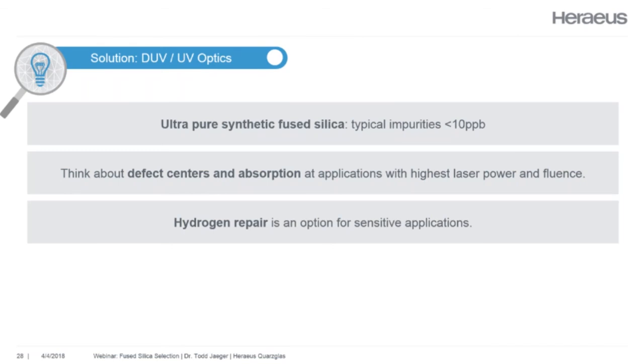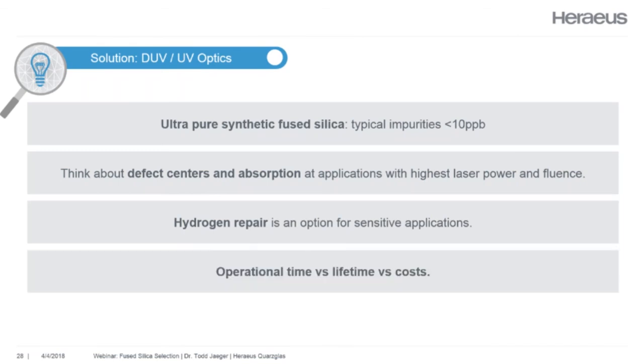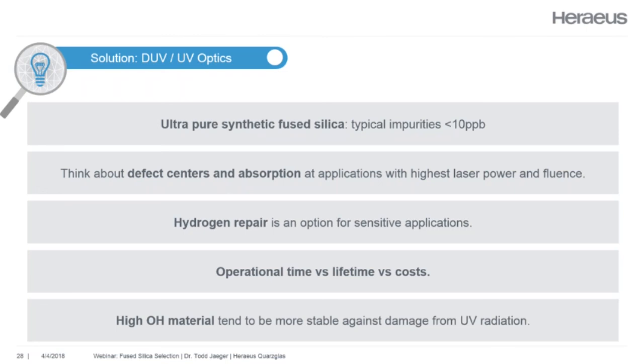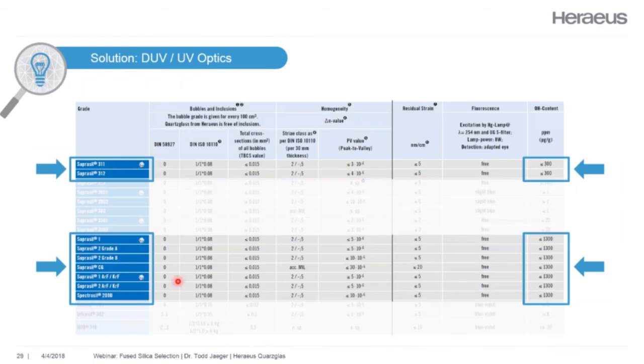These are special materials that are hydrogen doped that we can make on request. So you have to consider the operational time versus the lifetime you're looking for and the cost of ownership for the system. One thing to note is that the high OH materials tend to be more stable against damage for UV radiation. So if we go to the Heraeus spec sheet, once again, we're going to look for the dark blue boxes. And within the dark blue boxes, we're going to look at the OH column and consider ones that are higher in OH content. So the best ones are obviously going to be these ones that are greater than 1300, but certainly for some applications, the Suprasil 311 and 312 work extremely well.